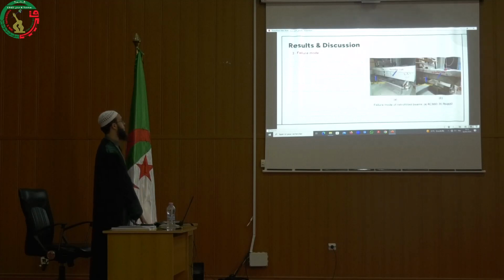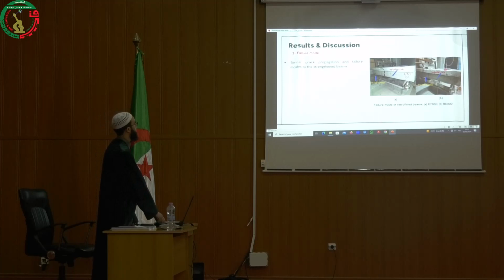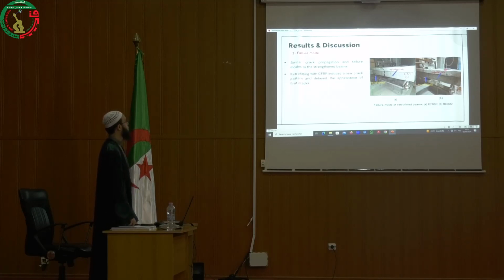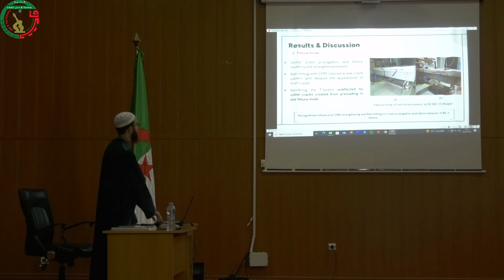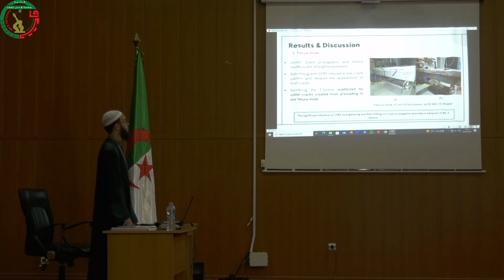The following pictures show the failure mode of the retrofitted beams. Similar crack propagation and failure modes to the strengthened beams were observed. The retrofitting with CFRP induced a new crack pattern and delayed the appearance of first cracks, which rendered the beam unaffected by initial cracks created from loading in the failure mode. This indicates the significant influence of CFRP strengthening and retrofitting on the crack propagation and failure behavior in reinforced concrete beams.